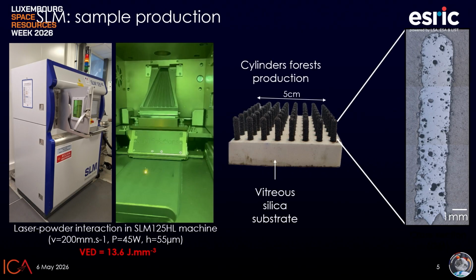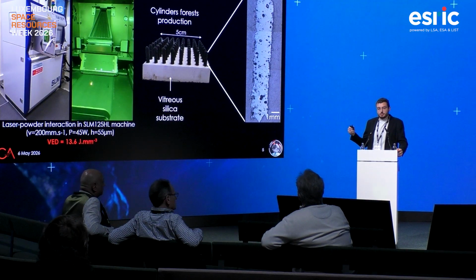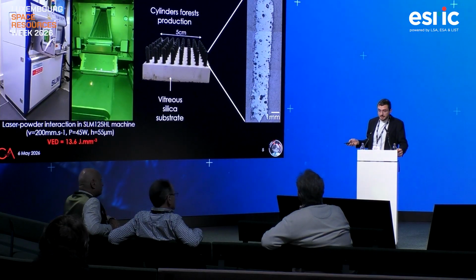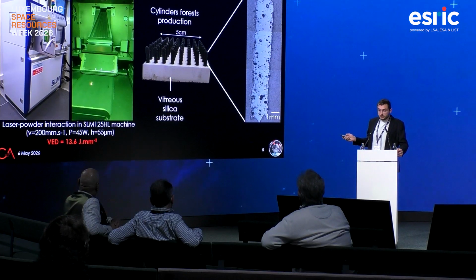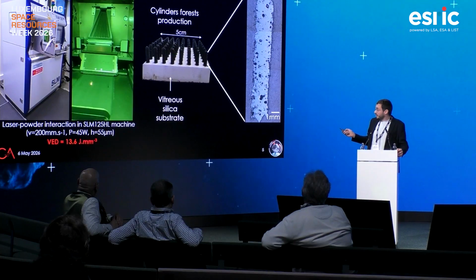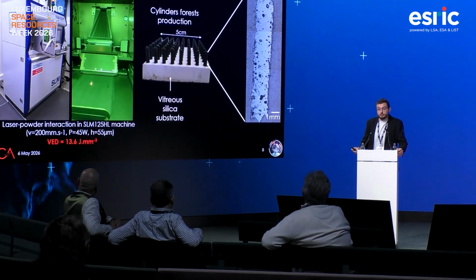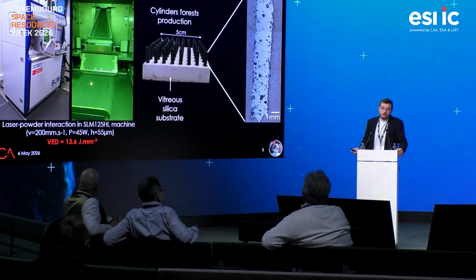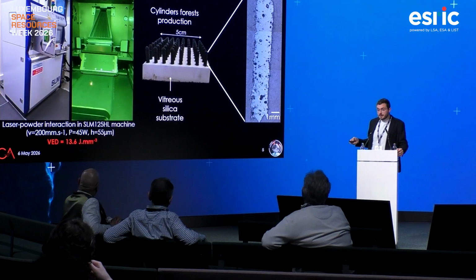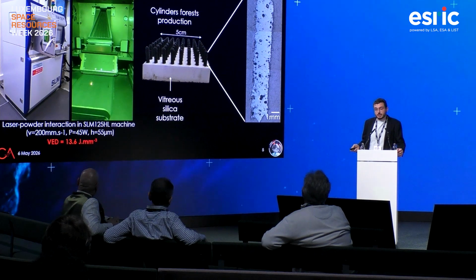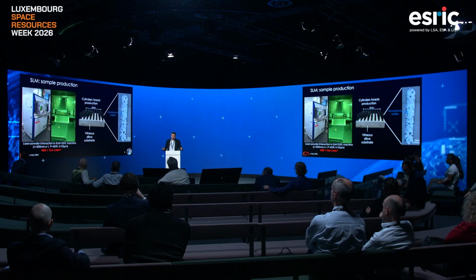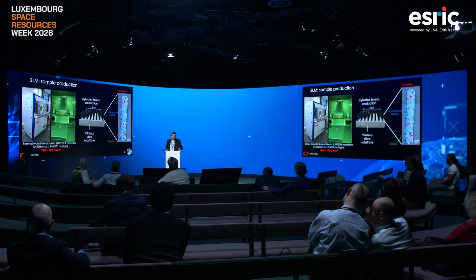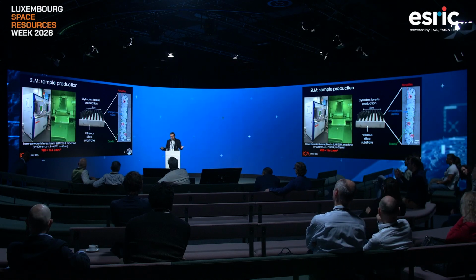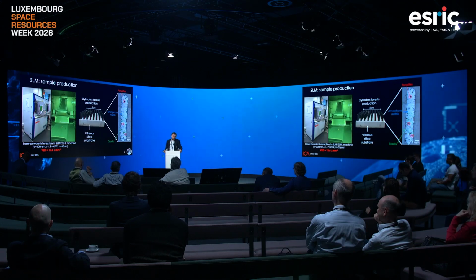So here you have the process. We use a commercial SLM machine from SLM Solutions. You've seen a lot of presentations about this, so I won't go into much detail. You have your powder layer exposed to a laser, you melt it, and then it solidifies. And so you have those nice glassy samples, like you can see here. In our case, we use a vitreous silica substrate, and those samples here are cylinders we make for compressive strength tests, and we also use them, of course, for microstructure identification. They are 3 millimeters wide, and as you can see on the cross-section here, they have some kind of homogeneous matrix, but they also have, of course, some defects like porosities and cracks, but that doesn't have to be an absolute thing. There are some things we can do to mitigate those effects and those defects.